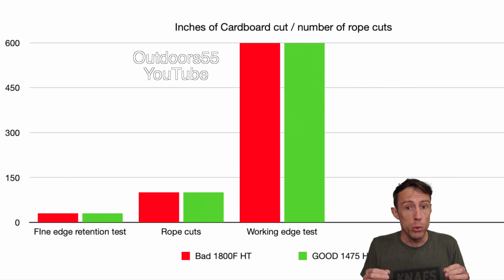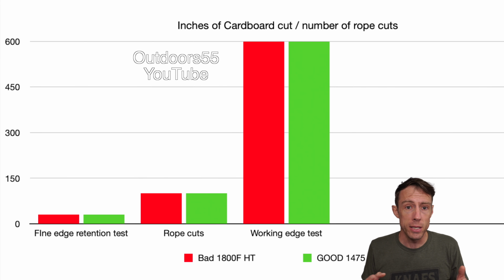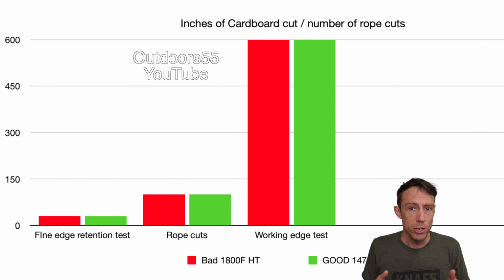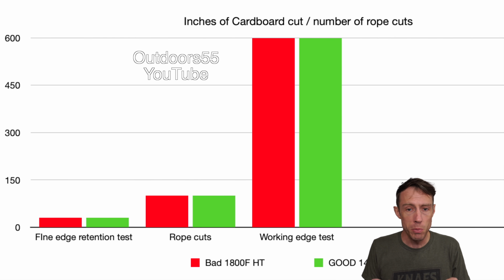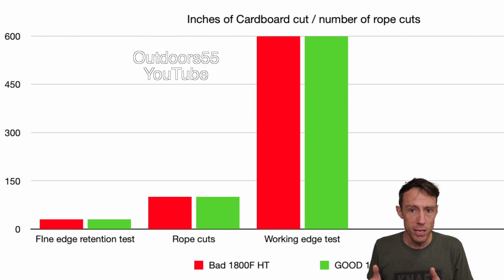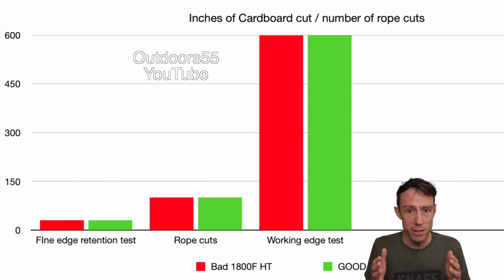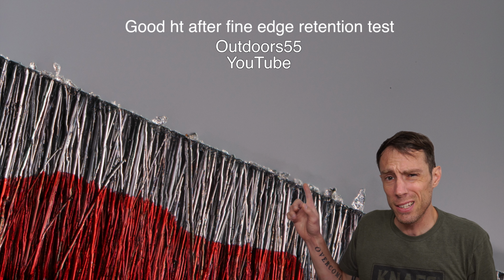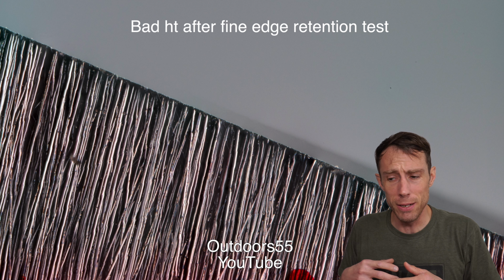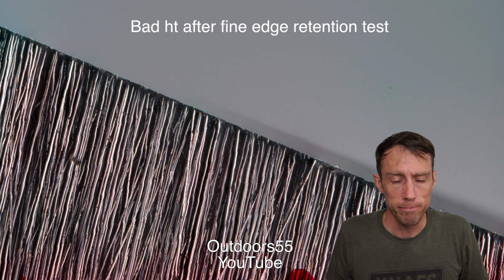I could not for the absolute life of me tell a difference between the two in terms of edge retention. Both blades, both the good heat treat and the bad heat treat, performed exactly the same. I mean, I even looked at the exact cutting area under the microscope to see if we could see any difference whatsoever. We still can't.